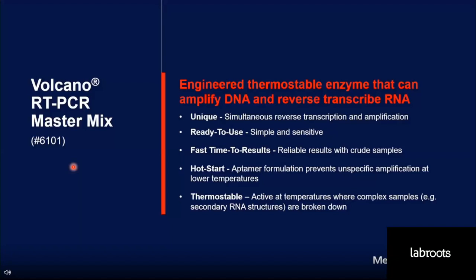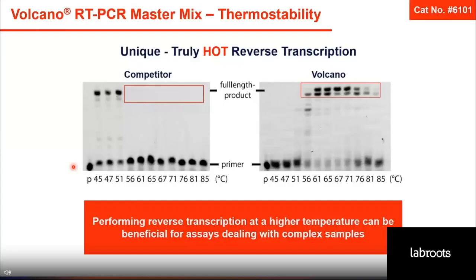And importantly, as the reverse transcription takes place at higher temperature, we recommend Volcano for very complex samples with secondary RNA structures, because when you perform reverse transcription at higher temperatures, you do not observe these secondary structures of RNA anymore. So to show you how hot the reverse transcription with Volcano is, this is a comparison analysis of primer extension assay for standard reverse transcription and for Volcano. So standard reverse transcriptase, as expected, does not perform any extension above 50 degrees. However, the optimal temperatures for Volcano range between 60 to 75 degrees.